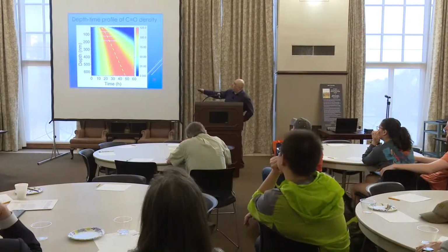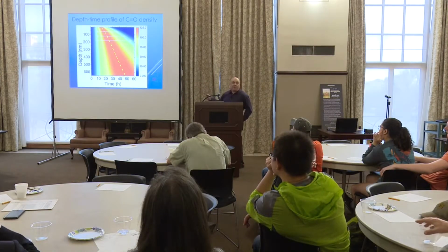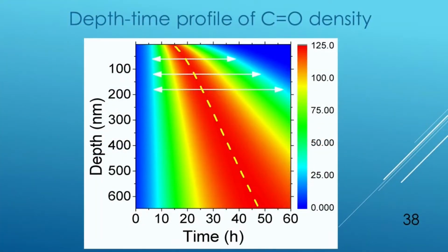This graph tells us the depth time profile of the carbonyl density. If we look at the top, we are looking at the top of the film. That's where it gets the sunlight directly. There we see in the beginning the carbonyl density is almost 0, but as time goes, at 5 hours, we see some significant generation of carbonyls. And they maximize, and then they actually fade. So in 20 hours, that very first layer of the polymer is gone, okay?